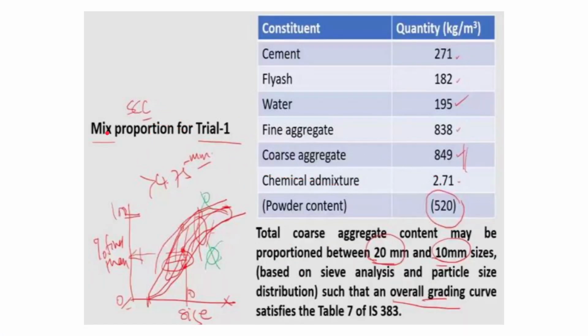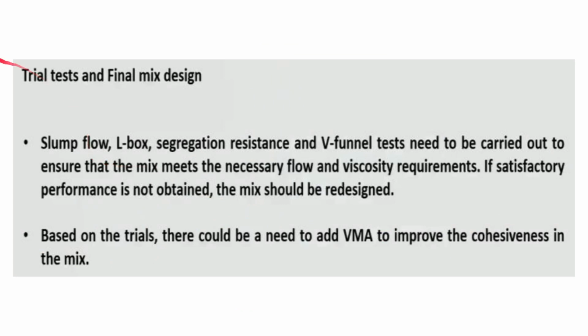From there, for the mix proportion for trial 1, we get these as the quantities. So this is how the mix proportion is done. The total coarse aggregate content may be proportioned between 20 and 10 mm sizes, based on sieve analysis and particle size distribution, such that the overall grading curve satisfies Table 7 of IS 383. As per our fundamentals, we have to proportion the coarse aggregate between 20 and 10 mm sizes as per the curve mentioned in Table 7 of IS 383. Finally we have to do the trial test and final mix design.